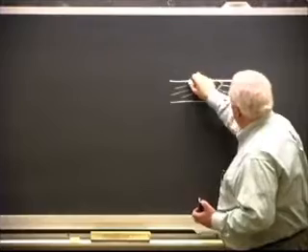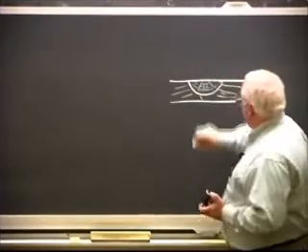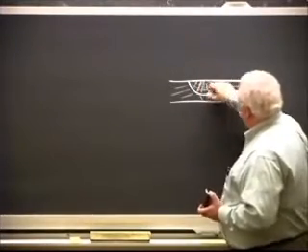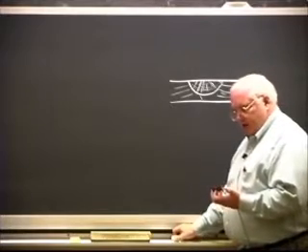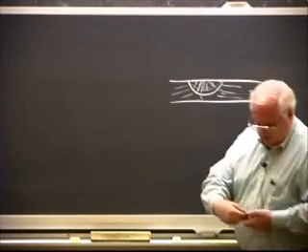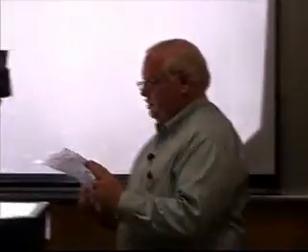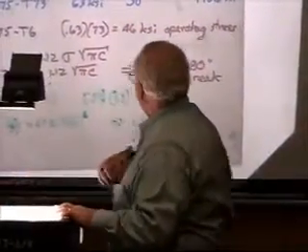You can't see, but if I went into an electron microscope, I could find the beach marks there, but you'll see kind of this little thumbnail shaped region if you get it at the right area of the light, and it's literally, I'd prefer you not put your thumbnail over it, but it's about the size of a thumbnail. And it goes about 80% of the way through the thickness of this thing, okay? So that was the problem. I said, oh, well, it's a fatigue crack. This thing's messed up at the bottom anyway. Well, I'll have to redo this some other time.